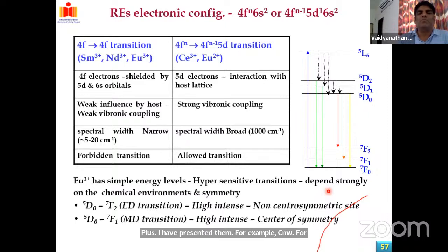A small amount of calcium can be replaced by the europium 3+ ion. So we can get emission from the europium 3+ ion because it is located in the 8 coordination with a non-centrosymmetric site. Hence we can get the electric dipole transition, which is the red one here, 5D0 to 7F2. The orange emission, the magnetic dipole transition 5D0 to 7F1, is higher when the europium 3+ ion is present at a perfect centrosymmetric site.